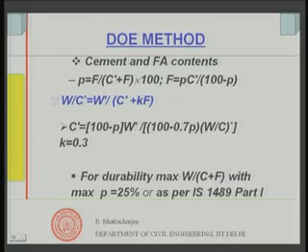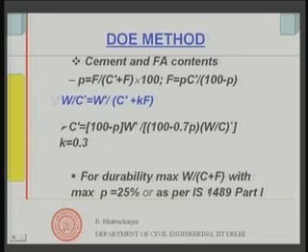Portland pozzolana cement now allows 25% as P, which means that 25% of the total cementitious material is your pozzolana, so you are using roughly two thirds cement, and one third is added as pozzolanic material, fly ash. Of course, this is likely to be modified; one might possibly use higher,